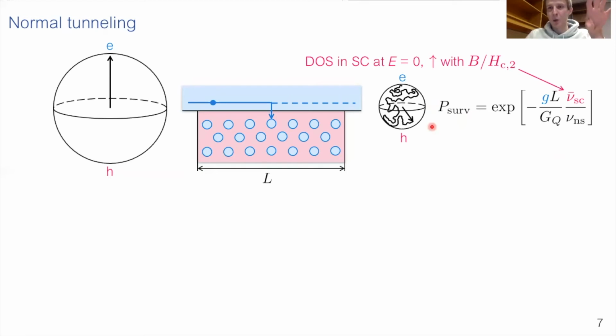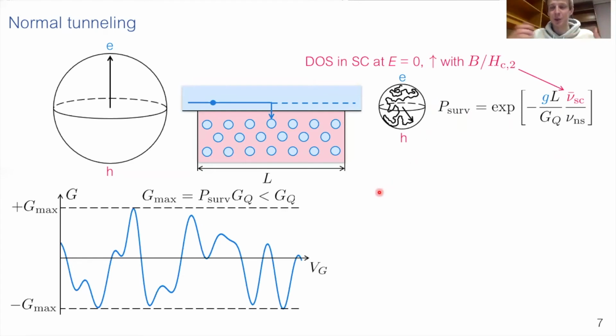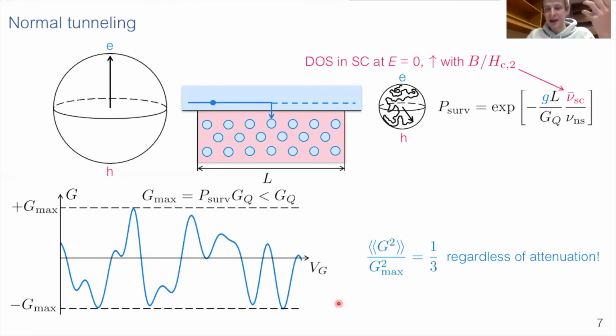In the language of our Bloch sphere, the fact that the probability to be transmitted is no longer 1 just corresponds to a shrinkage of the Bloch sphere. This shrinkage results in the attenuation of the amplitude of fluctuations. So it's no longer a quantum, it is something smaller. However, the spherical geometry is still there. So the statistical properties of the conductance distribution remain the same. For example, the relation between the variance of fluctuation and their amplitude that I described on the previous slide, this 1/3 relation, remains intact even in the presence of attenuation.